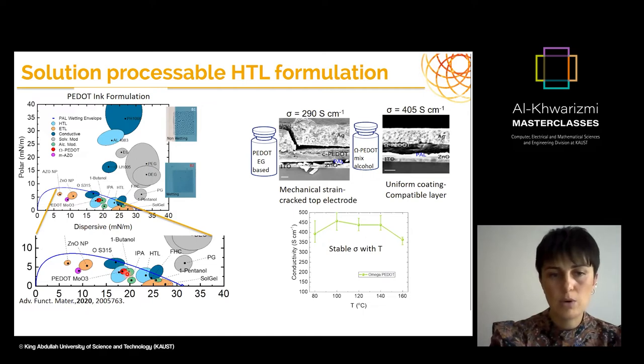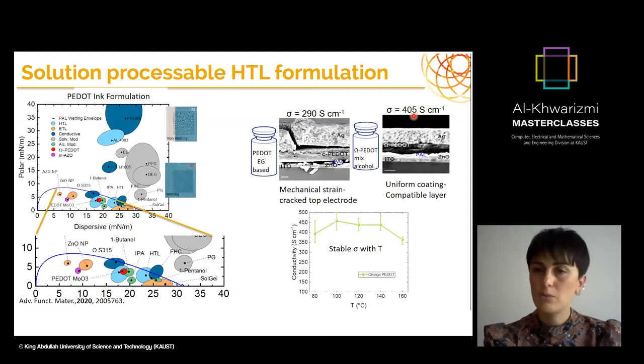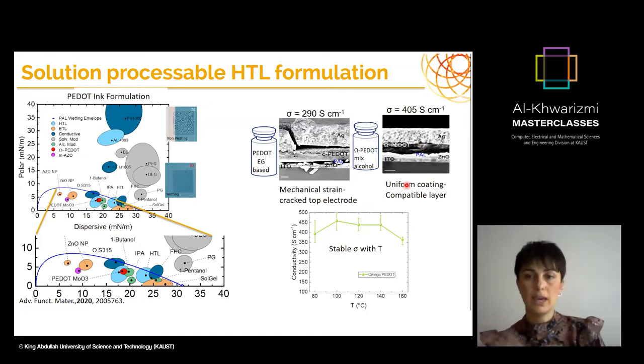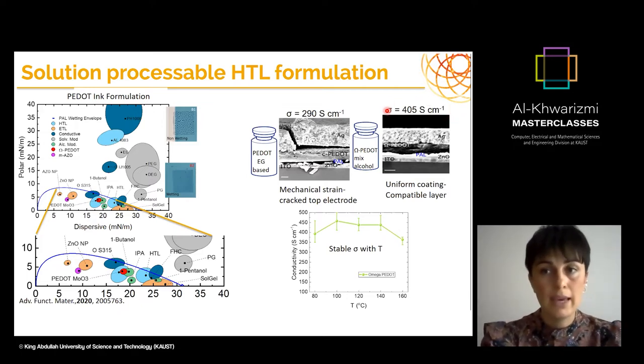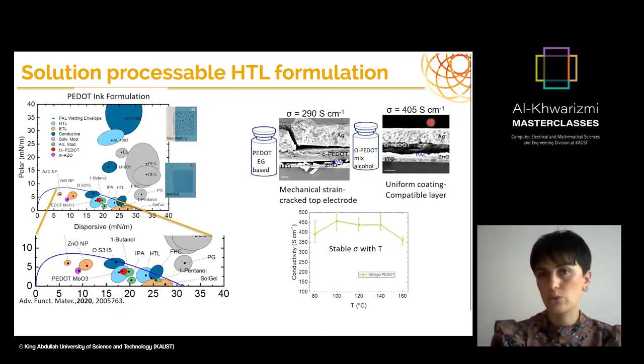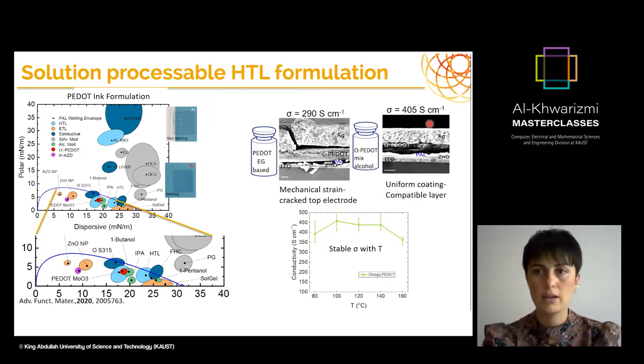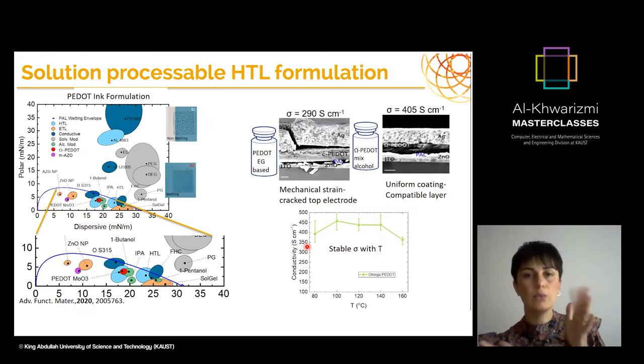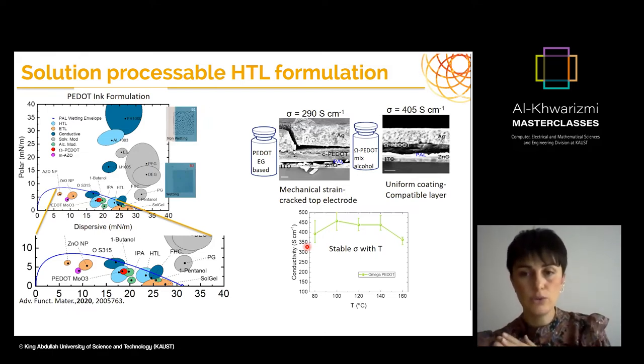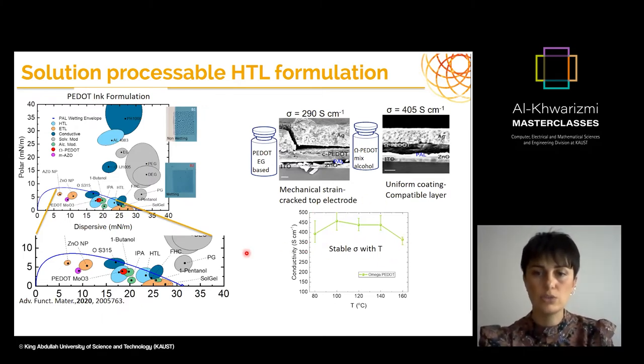We managed to find this sweet spot combination for ink formulation that is suitable for this type of photoactive layer. And when we put it on top of our layer, PTB7-Th-4F, we didn't see any mechanical strain, and we were able to have a uniform coating and printing. And also we were able to keep the decent conductivity that is required for the hole transport layer. Most importantly, we had to look at the conductivity with temperature, because on top of this HTL, when you want to apply the electrodes industrially, that also inserts some sort of temperature and even pressure. And with this, we ensured that it also works.